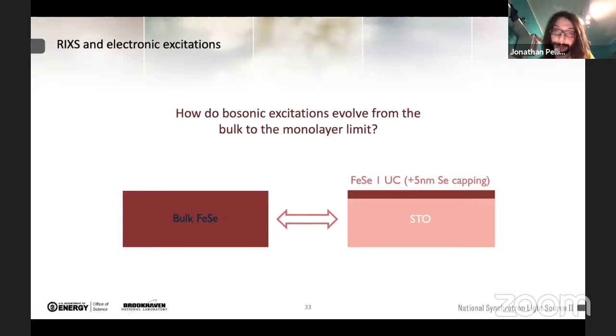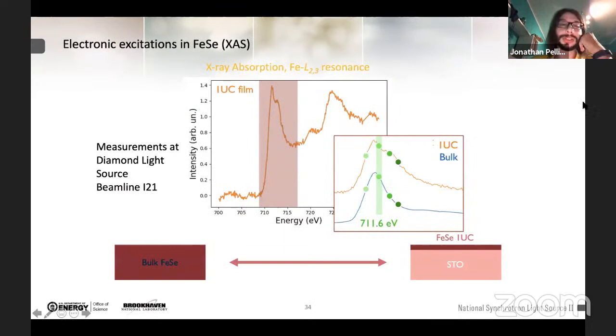So as I said before, the first step when we perform a RIXS experiment is to measure the X-ray absorption spectrum. And here I'm showing the X-ray absorption spectra at the iron L edge for the one unit cell film. First of all, this is a result that we were able to measure, to have spectroscopic measurements on the monolayer material, because the limited amount of material precludes any strong signal. And on top of this, we also measured the absorption spectrum of the bulk material.